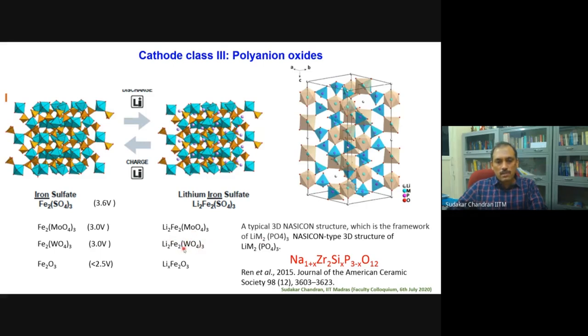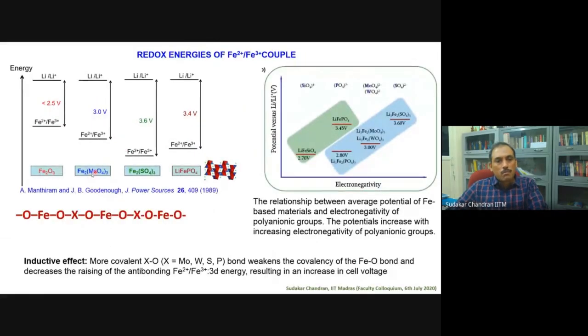So you don't have oxygen as an anion here. You have an MoO4 as an anion. So that's why it's a polyanion. And Manthiram found out that when he studied Fe2(MoO4)3, a polyanion, the voltage was around 3 volts, which is much higher than the iron oxide itself would give. Becoming curious, they also explored sulfate polyanionic compounds. These all exhibit the Nasicon structure, and they found that it exhibits 3.6 volt. So the voltage could be increased by changing the polyanion type.